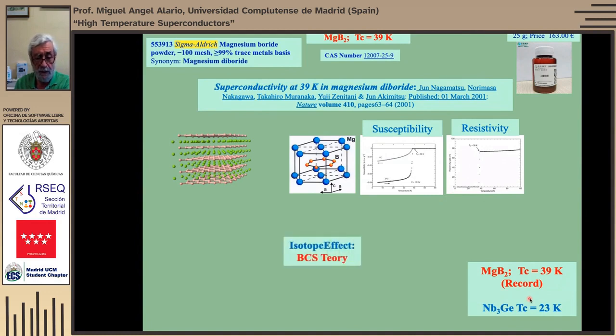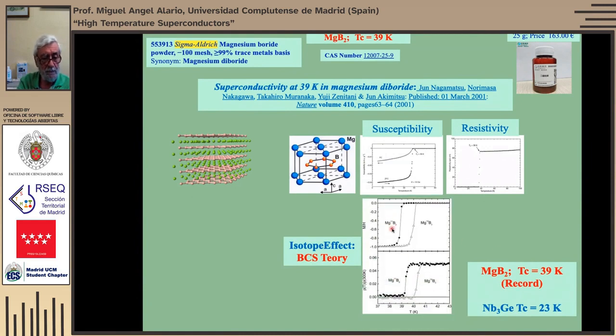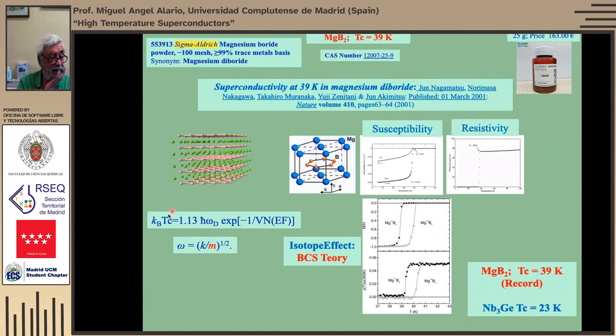That was the previous record for this type of material. Another interesting thing, which I briefly mentioned, is the isotope effect, which is that if you change the mass of the atoms, you change the critical temperature, because in the theory, which I'm not going to explain, the critical temperature, this is Boltzmann constant, depends on the Debye frequency. And the Debye frequency depends on the mass. So if you diminish the mass, you increase ω, and then you increase Tc.